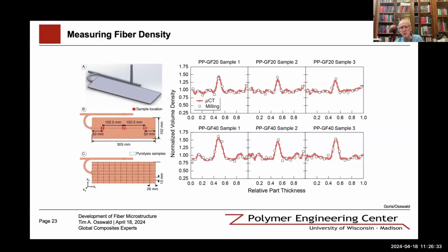These are injection molded parts using the Stamax materials, where the original fiber length is 15 millimeters. And you can see there are two different techniques used to measure the fiber density distribution. The red lines are micro CT, assessing the fiber density distribution that way. The second one, the little gray circles, is a more cumbersome way of doing it, but more exact: milling the part, burning the powder that is milled off, and then measuring the glass content after doing a pyrolysis analysis, so it's more accurate. But you can see both techniques, the micro CT and the milling method, give the same results.